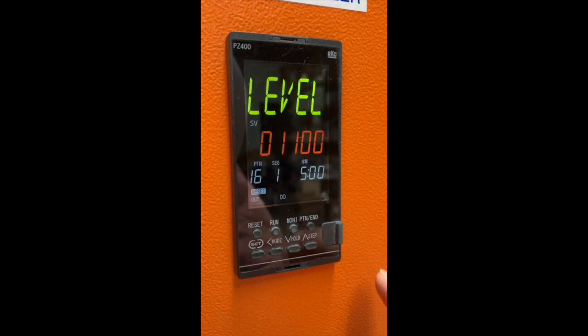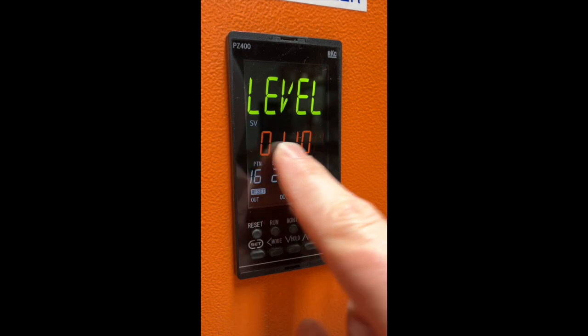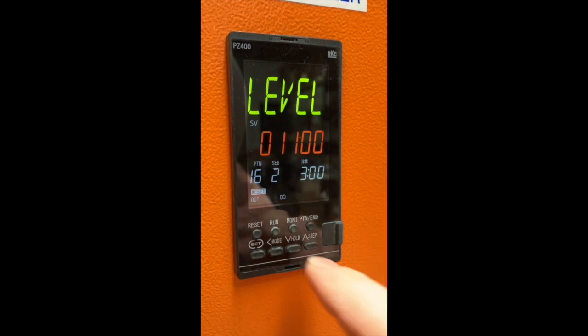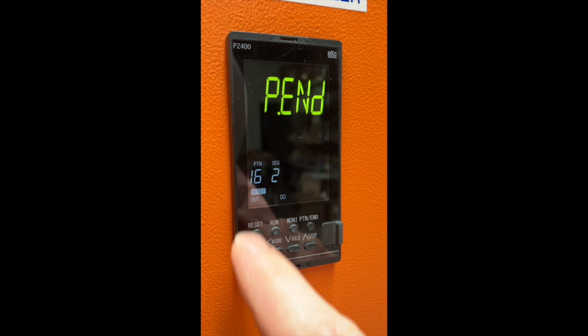So we'll hit set once. Segment 1, it's going to 1100 in 5 hours time. Segment 2, it'll stay at 1100 for 3 hours. And that's it. So it's an 8-hour program, and what you need to do is have the bung and the tile in until you reach 1000, then leave them out for the rest of the firing, including the cool down. I've been told from the manufacturer that this is preferable because it exposes the elements to more oxygen, thus giving them a better coat.